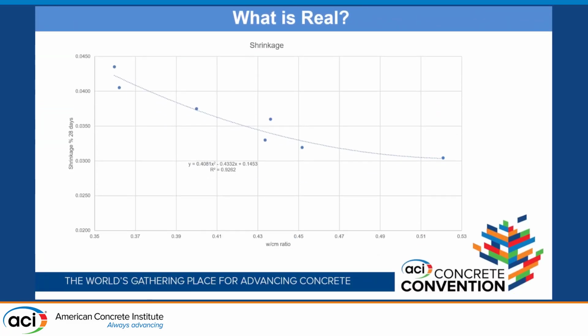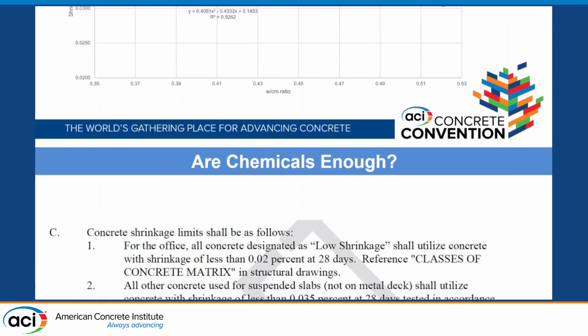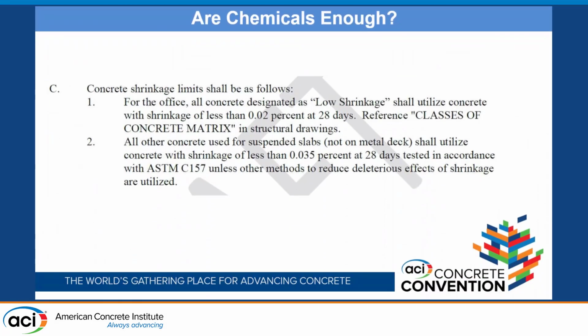So, what is real? This is a particular set of materials that I have in Texas. I ran different water cement ratios versus shrinkage, and just as everyone suspects, the more paste that you have in it, the more shrinkage you're going to have. That's not a shock to anybody, right? So we want to find ways that we can reduce the amount of shrinkage, but have enough cement content in the mix to make strength. So it's one of those competing factors against each other.